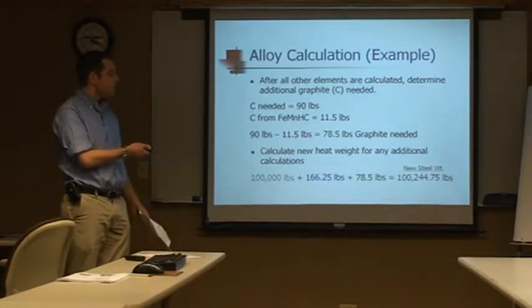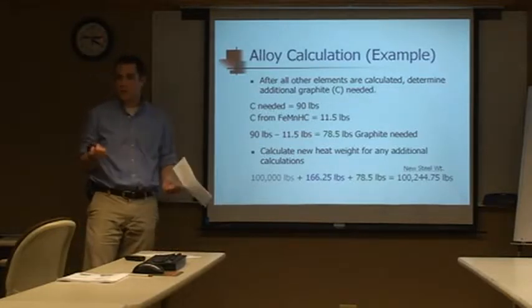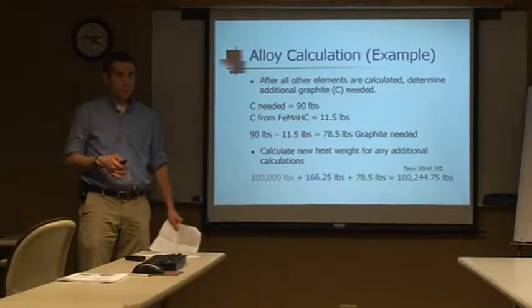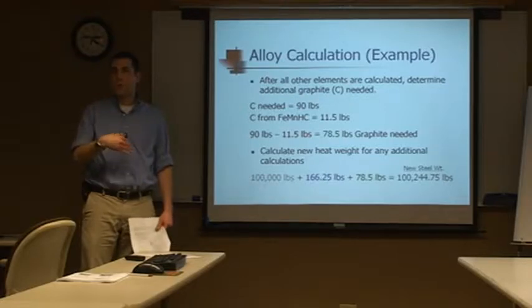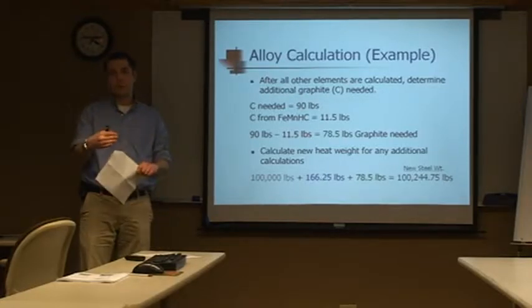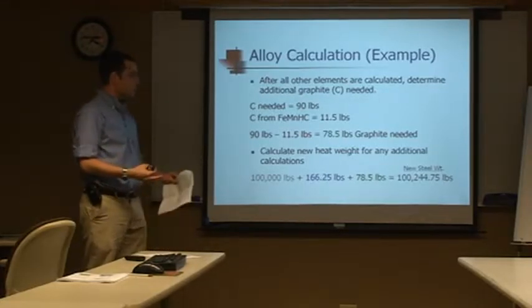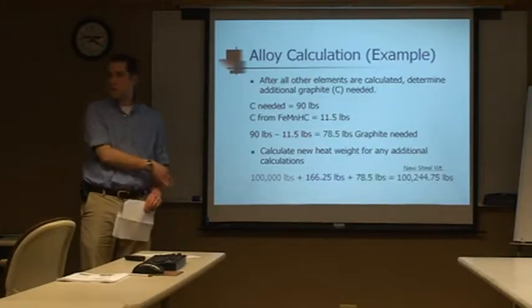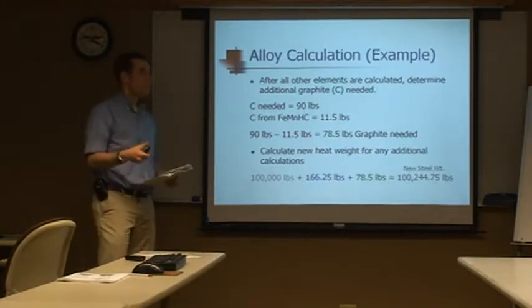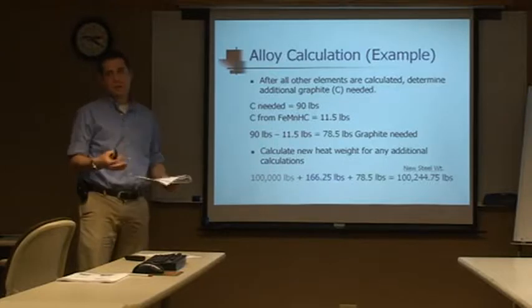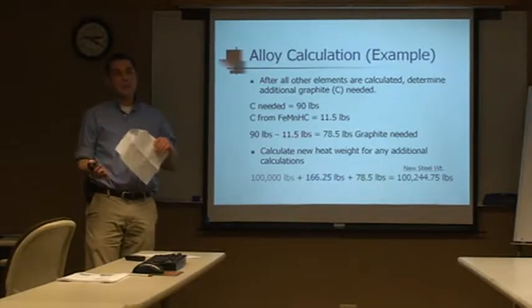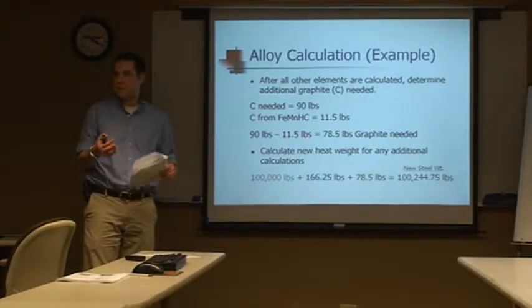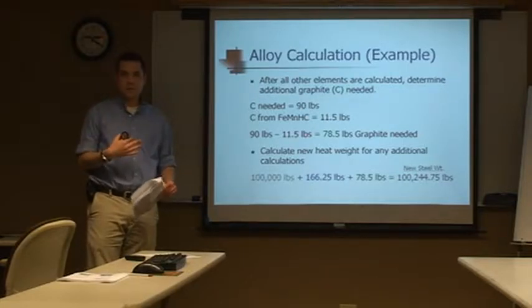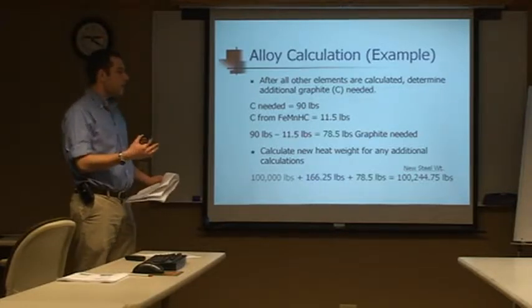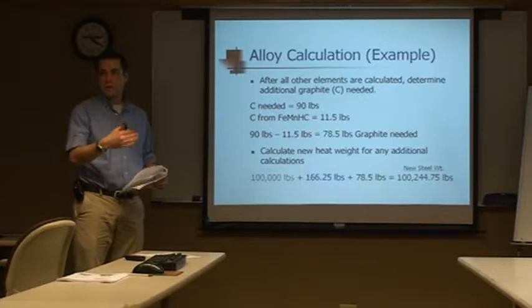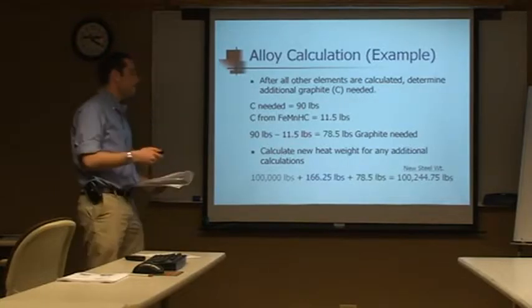And this is for a simple grade. For a more complicated grade like a stainless steel, we know we're going to have to do more than one add, because we got to creep up to our ranges rather than just trying to do them in one swoop, because we might exceed the maximum. And that gets really hard to fix, because then you got to add in dilution iron or something like that to dilute down your alloy content, which is much harder than adding alloys to get up into your content.